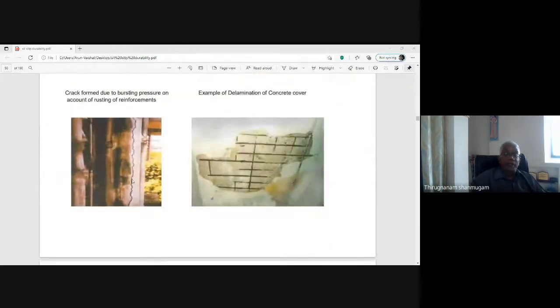This photograph represents the delamination of the cover concrete. The cover concrete is completely eliminated, and the steel reinforcement has cracked due to bursting pressure on account of rusting of the reinforcement. Example of delamination of the concrete cover, roof slab. The concrete cover is about 15 mm. So the mild steel is exposed completely.